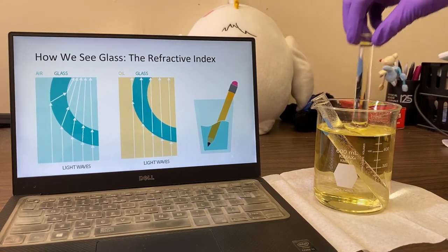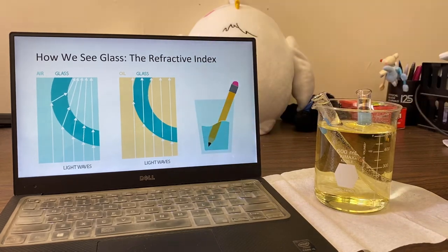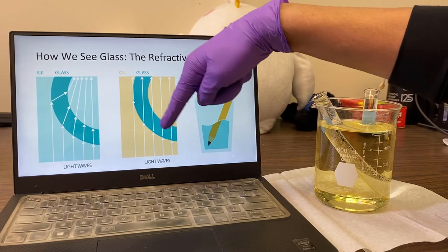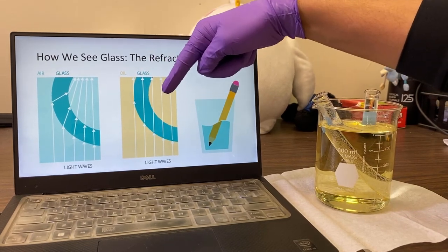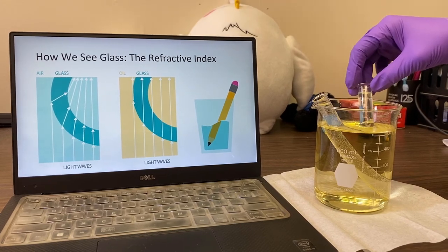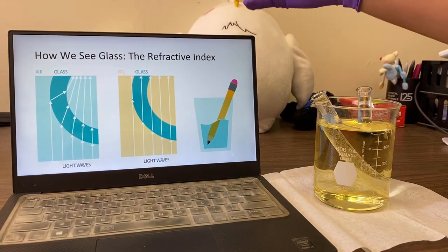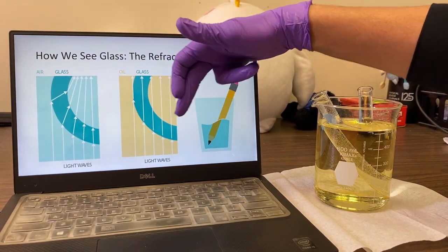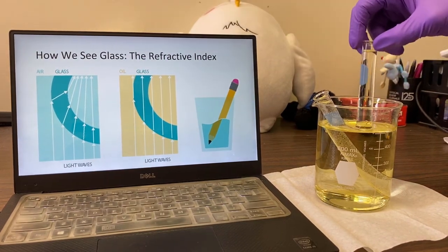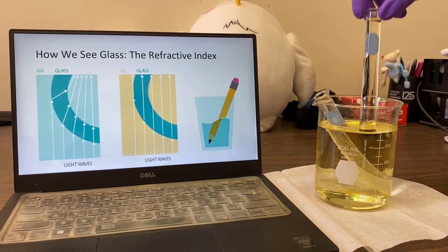However, for the oil one, light goes straight through and does not bend at all. It does not bend because the refractive index of the tube and that of the oil inside and outside the test tube are the same. The refractive index — which is the optical property of the material — of the oil inside, outside, and the glass are all the same. If they have the same refractive index, light just goes straight through and you can't see it, like here.